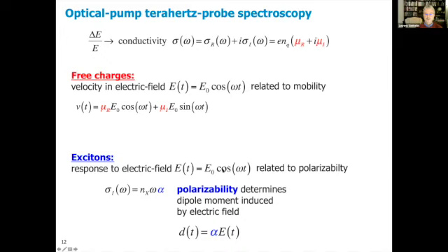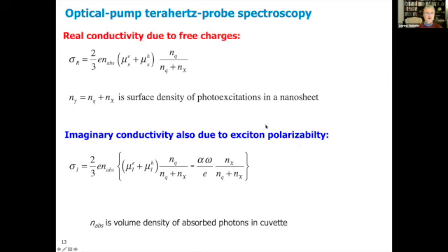So we have a field E naught cosine omega t, then you can induce a dipole moment which is proportional to this electric field, and the proportionality constant is known as the exciton polarizability. And that contributes to the imaginary component of the conductivity. So altogether, we get a real conductivity, which is the sum of the electron and the hole mobilities times the quantum yield, the number of charges divided by the number of charges and excitons.